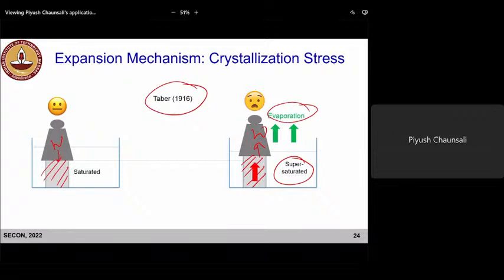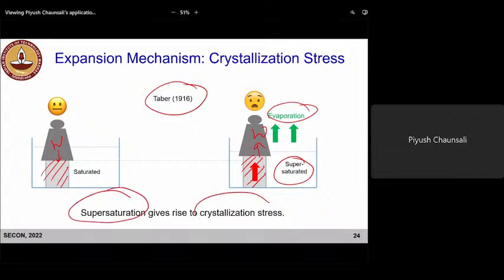So what is the driving factor for crystallization stress? It's the supersaturation. So supersaturation gives rise to crystallization stress. That's why it's important: if we can somehow estimate the supersaturation, we will get an idea about what degree of crystallization stress is there in the cementitious systems.